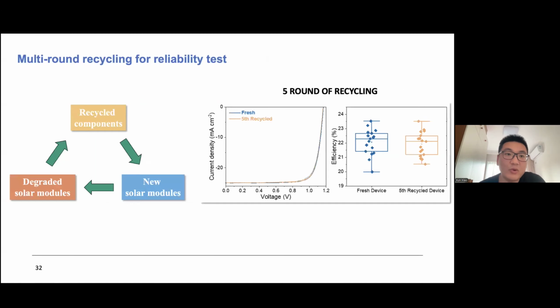More interestingly, we used multi-round recycling for reliability. That means we recycle the degraded perovskite module, and then we use the recycled components to fabricate a new module, and then the new module will be degraded again. This is one cycle, and then we do this cycle five times, and then compare the device efficiency. It can be comparable with a fresh one.